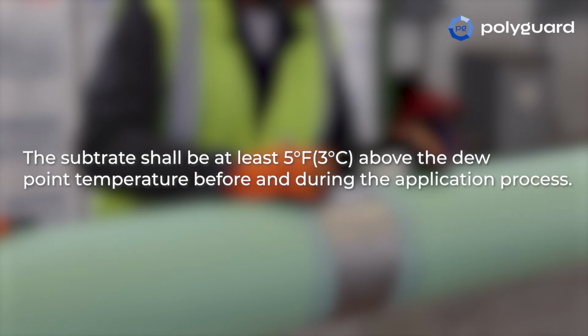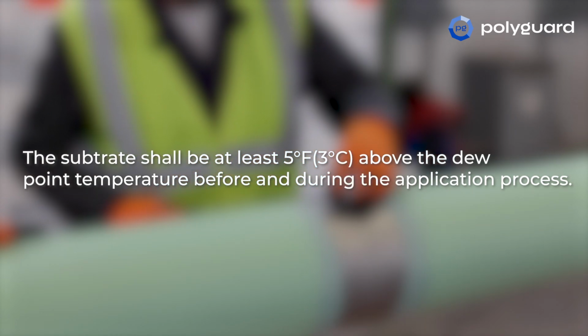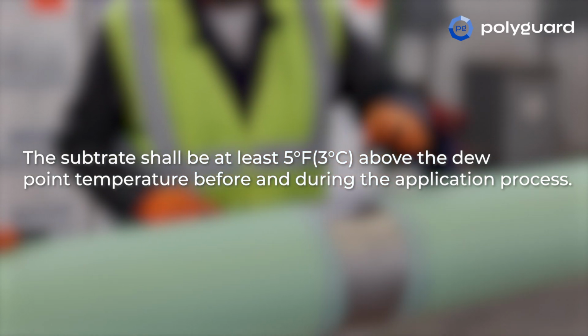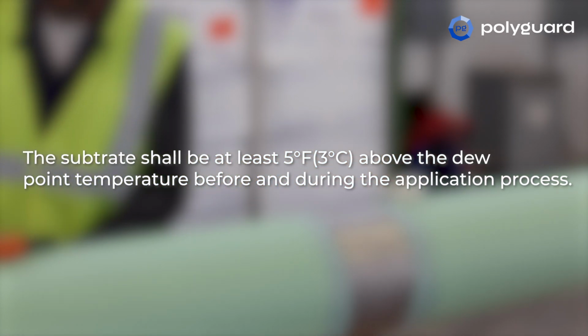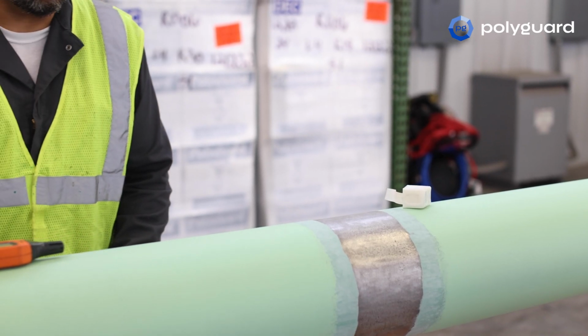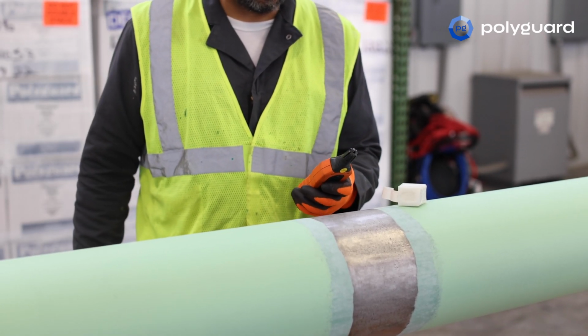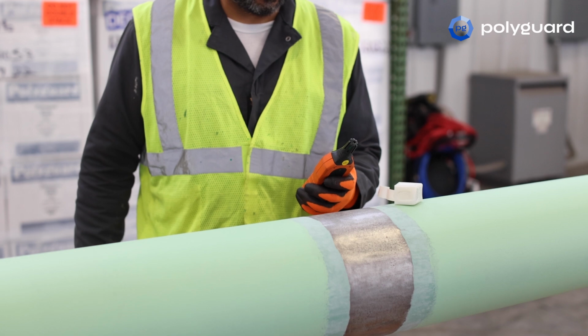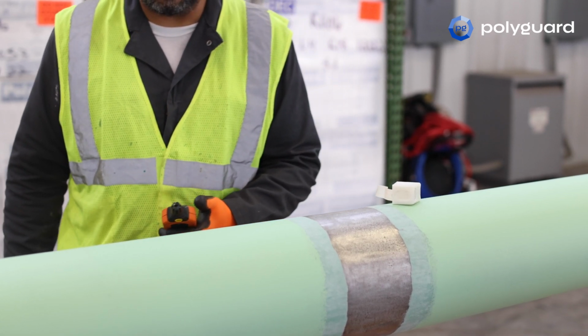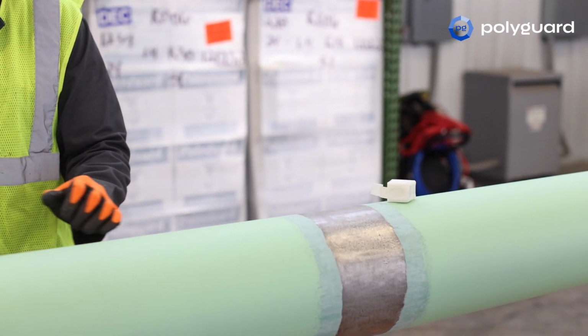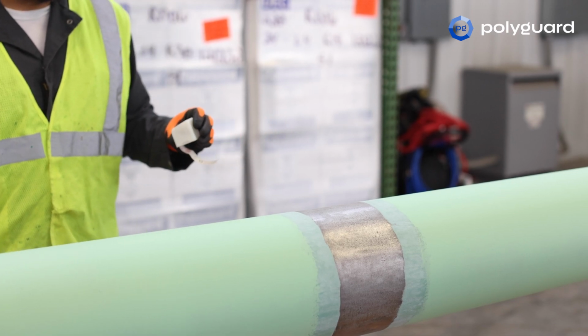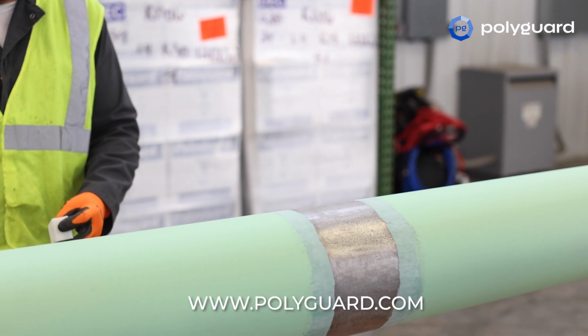The substrate shall be at least 5 degrees Fahrenheit, 3 degrees Celsius, above the dew point temperature before and during the application process. Preheating of the pipe may be required to meet these conditions. The optimum surface temperature is 70 to 100 degrees Fahrenheit. Temperature details can be found on Polyguard's website in the RD-6 coating system application specification.